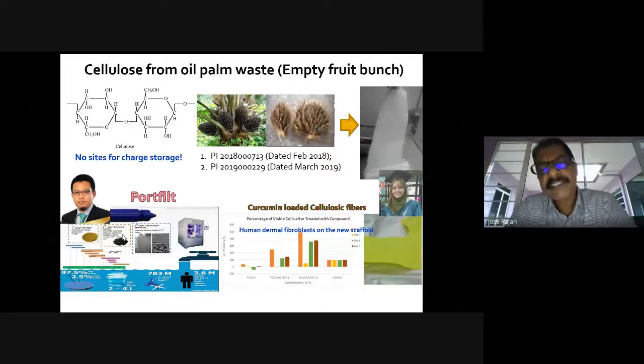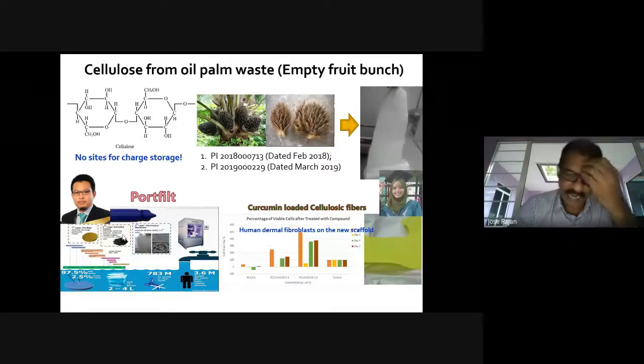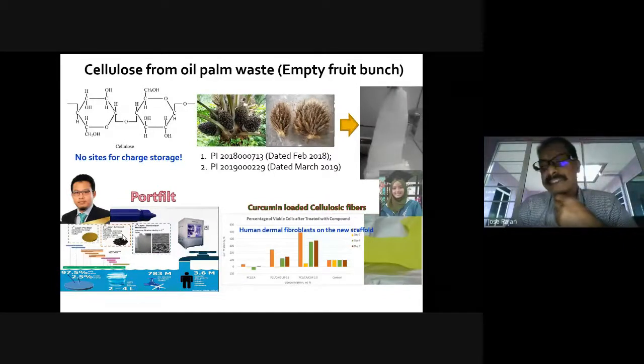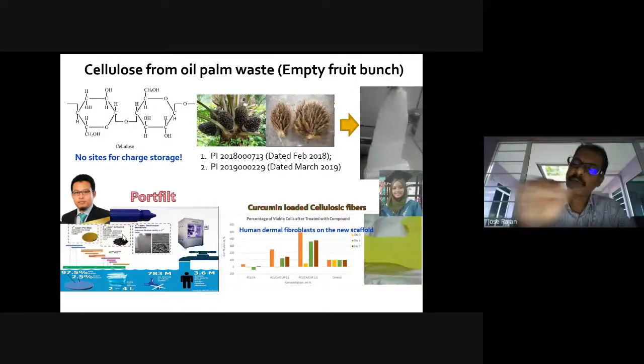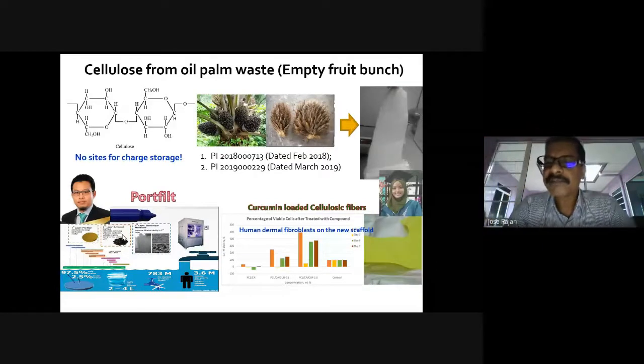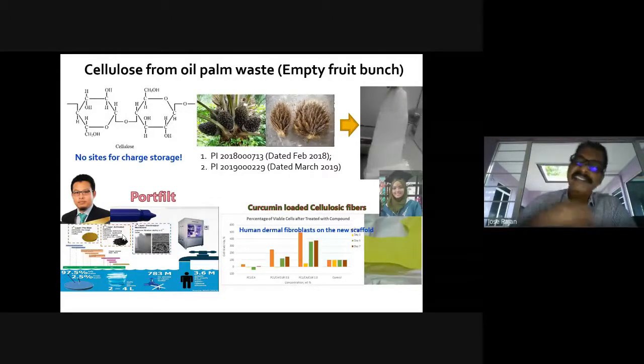And in another development, this starch is added with curcumin. Curcumin is the active ingredient which is anti-cancer, antibacterial, antiseptic. Curcumin has a lot of medicinal properties, and it is discovered that the turmeric in Kerala has the highest amount of curcumin. So this girl on the right side has added some curcumin in the starch, developed a non-woven fibrous film, and used it as a wound dressing medium. And she has shown that when this fibrous scaffold is used as a wound dressing medium, the wounds recover faster than with material that doesn't contain curcumin or the natural product.